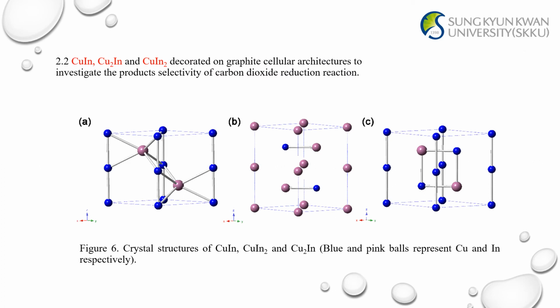Well, my second major research direction is research on carbon dioxide reduction catalytic materials. As we all know, in this field, the selectivity of the materials to the products of the carbon dioxide reduction reaction is particularly important. So I designed and synthesized three different kinds of copper-indium intermetallic compounds. Copper is the active site of the carbon dioxide reduction reaction. The copper atoms are bound to have different electronic structures in different structures, which will also affect the activity of the carbon dioxide reduction reaction. And so we synthesized three different kinds of materials to figure out